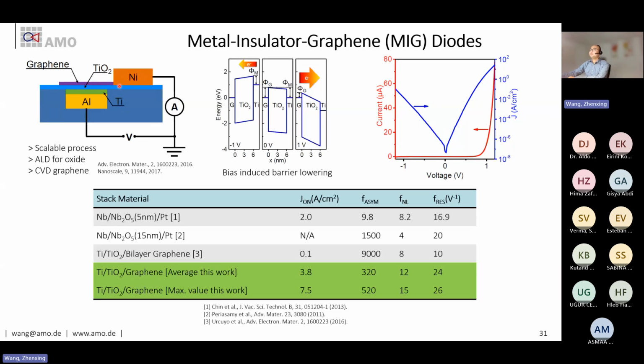For this, this is a scalable process, since we use ALD for the titanium oxide, and we also use CVD graphene. Actually, for the first work, I have to mention that this is not from us, it's from this work in 2016 from the Max Planck Institute in Stuttgart. We extended this work using scalable materials. We proved that it has really good quality as well in 2017. So this is the performance, and we can see that in general this device has very good performance.